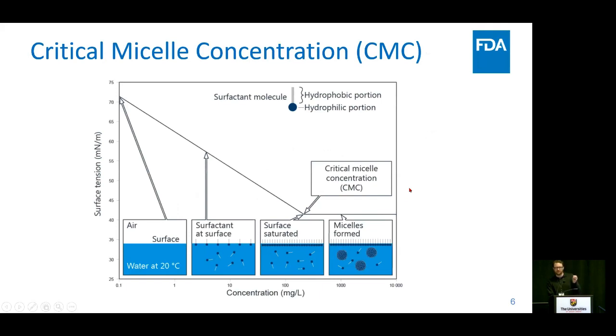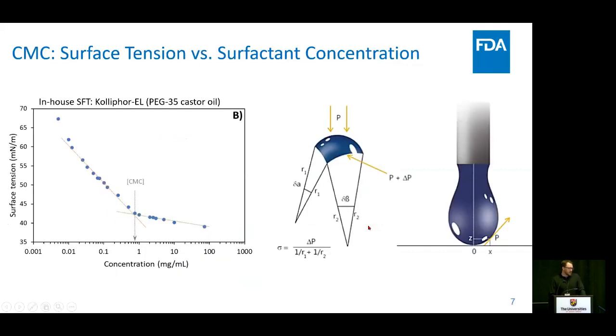First of all, hopefully most of you have some idea of what critical micelle concentration is, but basically it's the propensity for a surface active agent or a surfactant to migrate to an interface. As you incorporate surfactant, you get to the point where the surface is saturated with that surface active agent, then any excess surfactant begins to aggregate into a dispersion, and those are called micelles. This is important because beyond the critical micelle concentration, the propensity for a drug to solubilize or disperse into the formulation is more or less proportional to the concentration of micelles.